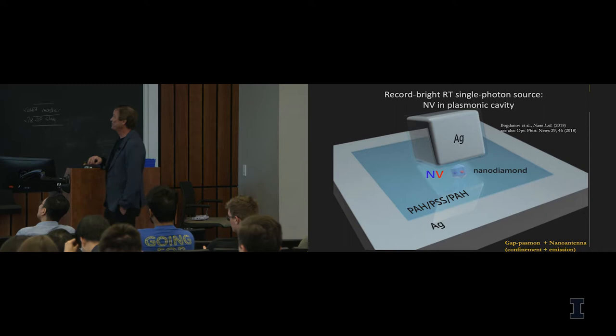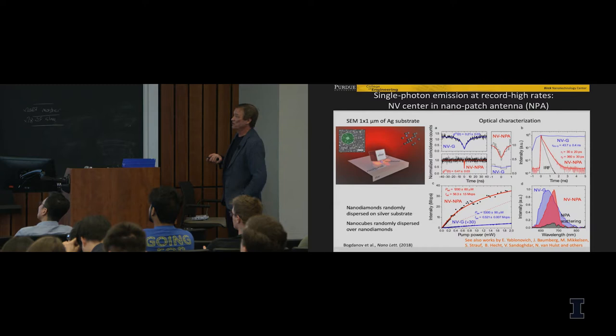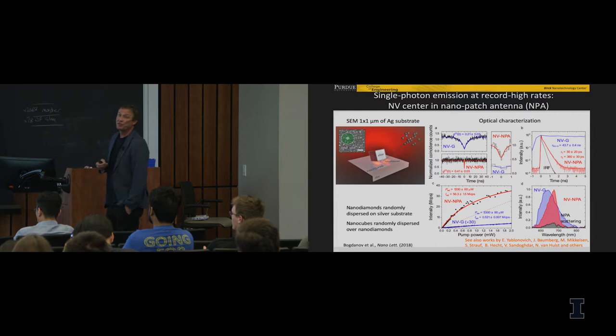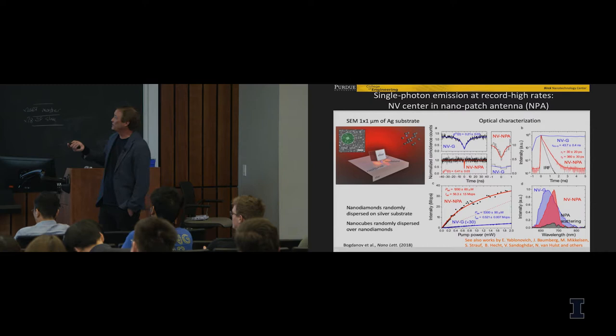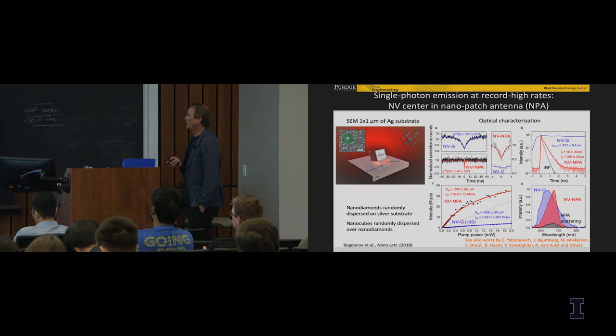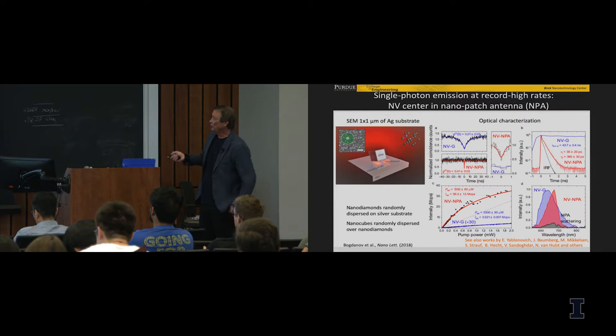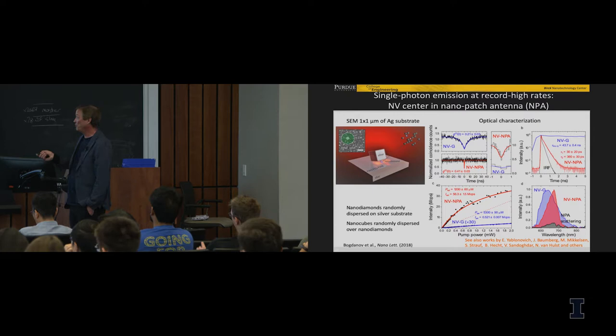First, let me show what kind of experiment we already did. In this case, we just randomly distributed nanodiamonds on a silver surface, then randomly distributed nanocubes. In some cases, just accidentally, you have the situation where a nanodiamond is sitting between the cube and the silver surface. And we do this measurement of G2. G2 is the correlation function. When you have this dip going below 0.5, it means that you're dealing with a single photon source. What we obtained is that, compared to nanodiamonds on glass, in this situation you actually have a dramatic increase in the rate with which you produce single photons, up to 30 million photons per second. At room temperature, actually, it's a record.